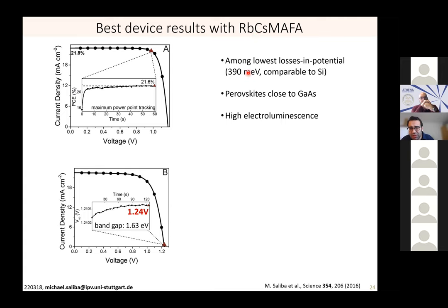And it was a very low loss in potential, 390 millielectron volts. I even was very conservative with the bandgap here, to be honest. I think it was lower. This was from electroluminescence. So it indicates this is comparable to silicon, but it also indicates that perovskites are more on the way towards gallium arsenide in terms of their potential. And this record has been broken since as well.